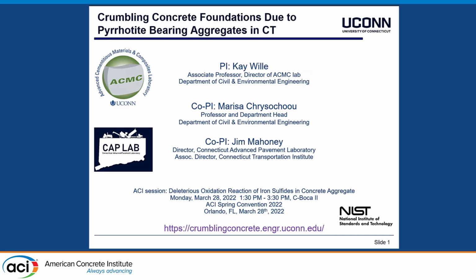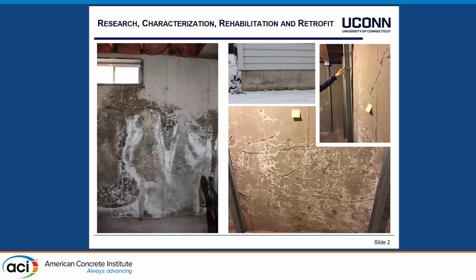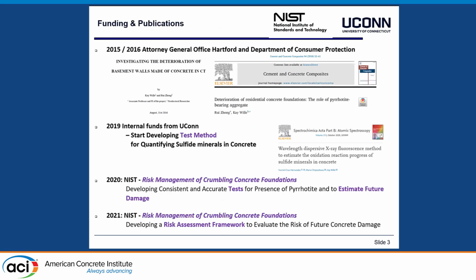So great presentation we have seen prior to this, and just rounding up with another presentation here about the research and investigation we do in Connecticut. So you have seen those pictures, and that's my arm there measuring the deformation of a concrete wall, but this is what you see if the concrete is deteriorated. A lot of cracking, especially those horizontal or map cracking. You have some whitish deposit there near the cracks, and so you can investigate all of this.